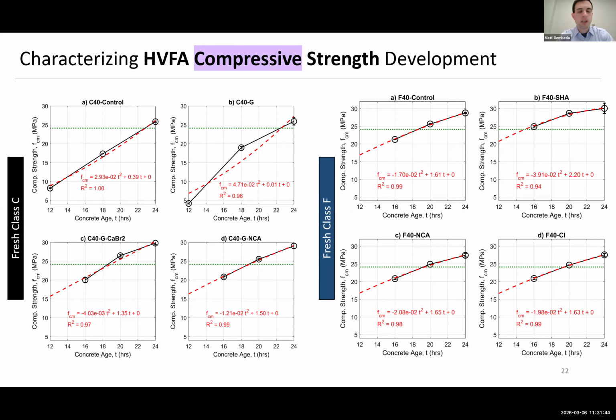The more interesting way to look at the data is plotting it over time to look at the strength gain. What we tried to do here was basically extrapolate the data points that we had to form these curves that could help generalize for these types of mixes what the strength gain profile would look like. So if you had a specific compressive strength target, it could help in the preliminary mix design stage for a precaster to estimate approximately at what age they would be able to get that value. Now, it doesn't replace testing in a plant. They're still going to have to do it for their own mix, but it was a preliminary thing that could help inform how to hit those early strength targets.